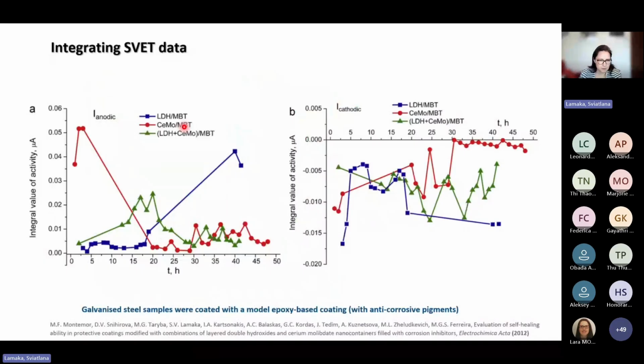I tried these commercial microprobes, and I'm not affiliated with the company in any way, I'm just sharing my user experience. We tried these commercial pH-sensitive microprobes from Unisense, where the tip of the microprobe is really made of pH-sensitive glass. It's the same principle as you use for macro electrodes, the centimeter size pH-sensitive electrode in the lab. And so really the biggest advantage of these microprobes is that the readings are exceptionally stable. There is a very stable potential. There is no drift of potential, and this is the most important property of the pH electrode for me,